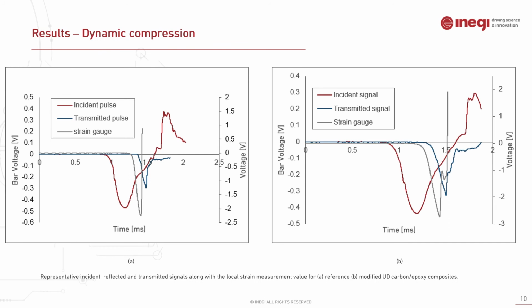The output from the split Hopkinson bar analysis is plotted for two material configurations, and we use one-dimensional wave theory to calculate the compressive stress value of the specimens, and we also use the locally bonded strain gauges to calculate the strain value, despite the fact that we could have used the one-dimensional analysis with the reflected signal. And also, as you can see, the profile of the incident pulse, we use a rubber pulse shaper to generate a sort of ramped triangular incident pulse, which is an ideal shape for testing composite materials and also brittle materials in general, which generates constant strain rate.